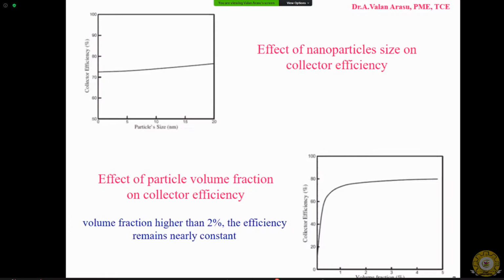And this shows how efficiency varies with particle size and volume fraction. Okay. So as particle size increases, collector efficiency increases, as against the previous results for the flat plate collector, where efficiency was decreasing as particle size increased. Then the collector efficiency increases as volume fraction increases, say up to around 1%, and thereafter there is not much increase in the efficiency. So this graph shows the optimum size of particle and optimum volumetric fraction of particle we can use in the actual system.